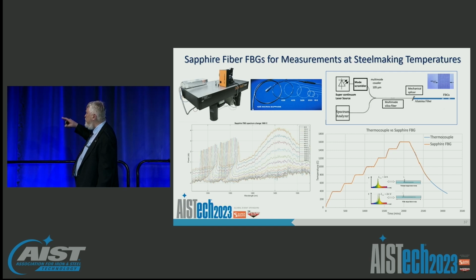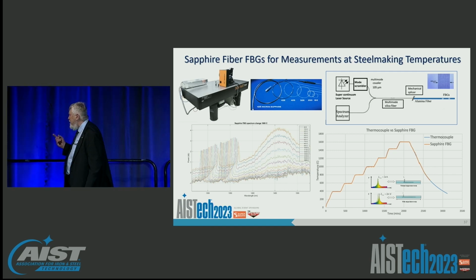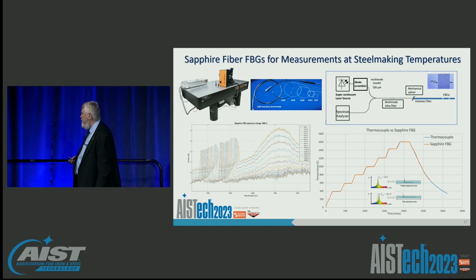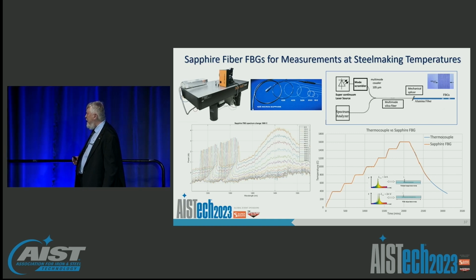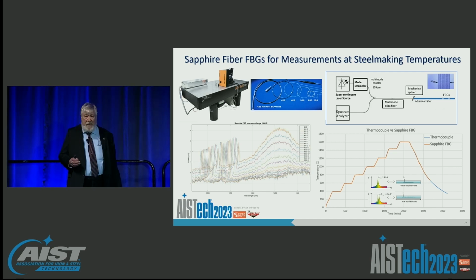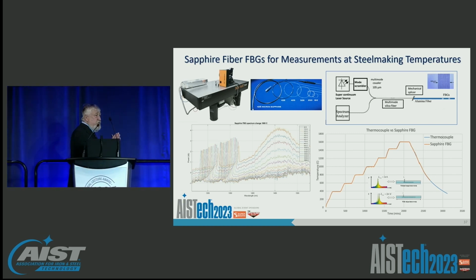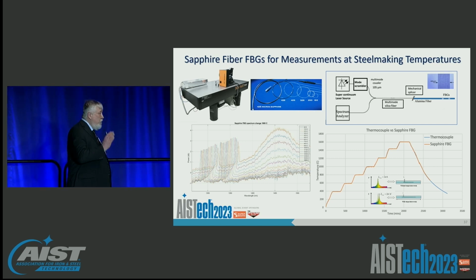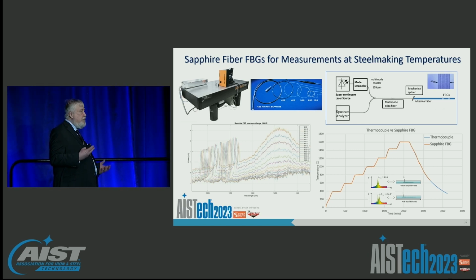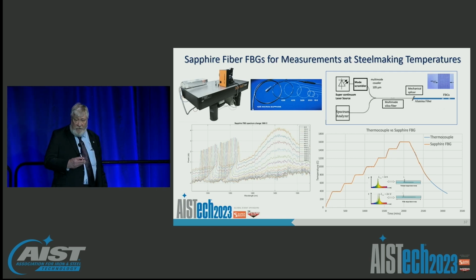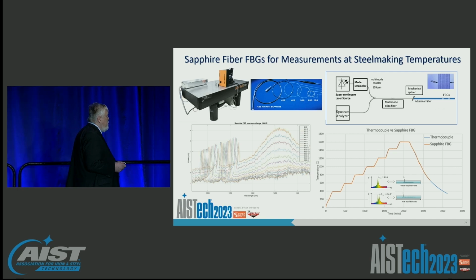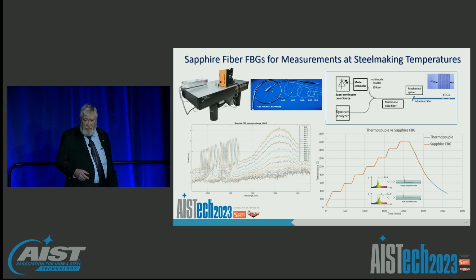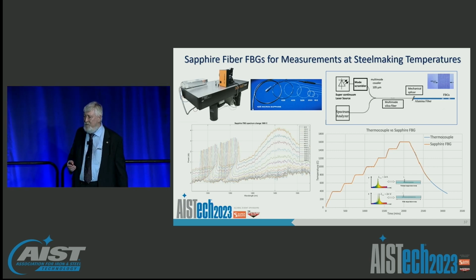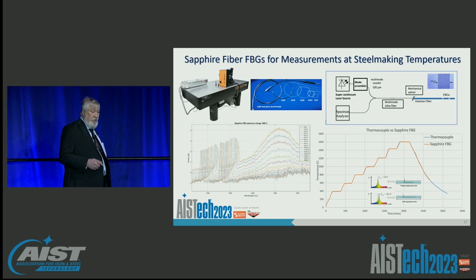The lower right shows a correspondence of the temperature measured by a Bragg grating with one from a type B thermocouple, just to show that these things track each other very well. This is actually doing a great job tracking the temperature changes in a system. On the left, you actually see the raw signals that show for 2 Bragg gratings, the peak shift is a function of temperature. That's what we're actually tracking to measure the temperature. So we monitor where these peaks shift to and then correlate that frequency shift directly to temperature. These can also be used for strain if you want to use them in a strain environment. You also notice there's a significant thermal emission that we see in the fiber because we're getting upwards to steelmaking temperatures at 1600 C. There's potentially applications for using that for information as well.